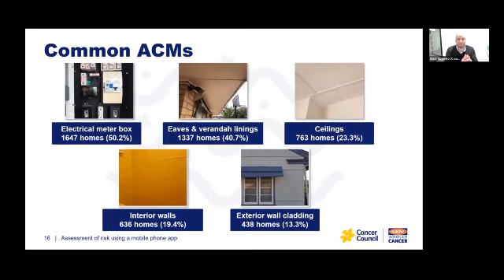Overall, the most common ACMs in the sample were flat asbestos cement sheeting used as the backing board to the electrical meter box, which was identified at around half of the homes, and flat asbestos cement sheeting used for the eaves, soffit lining, veranda ceilings, or the carport ceilings outside, which was identified at about 40% of homes.